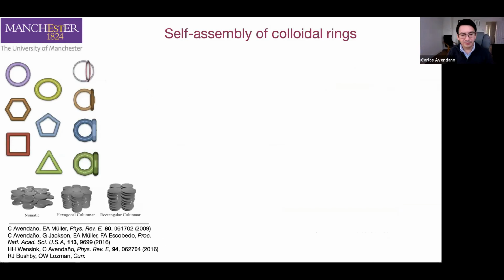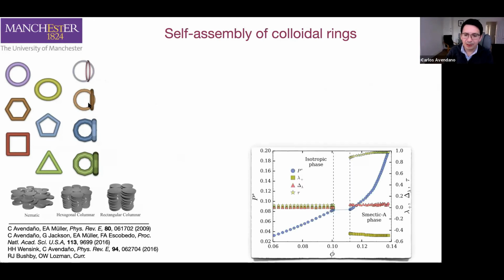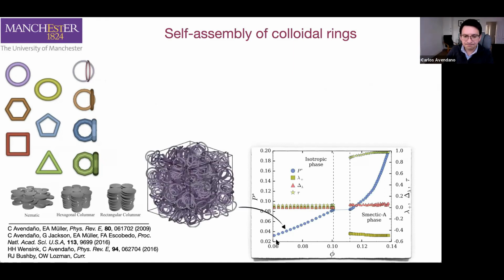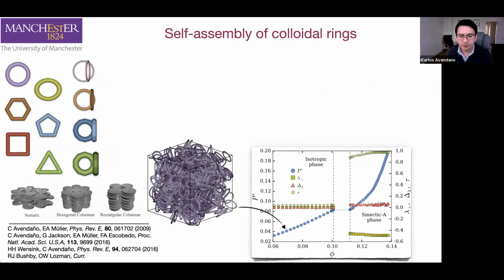So something that I was interested in working on with Fernando Escobedo, I was already in Manchester when we were working on this, but in collaboration with Eric Mueller, Fernando Escobedo, and George Jackson, we decided to study the phase diagram of these kind of particles. I will show you quickly what happens with a ring like this. So we ran some molecular dynamics simulations, starting first from a low pressure or low density system. When we run the simulations, we observe that the system just forms a typical isotropic phase. There is no order in the system.